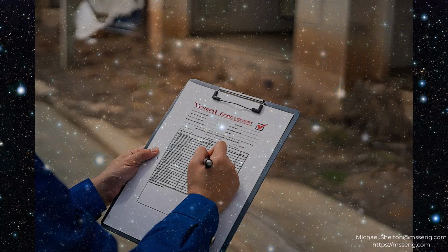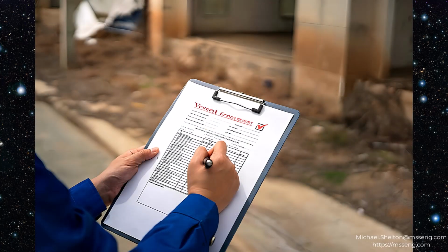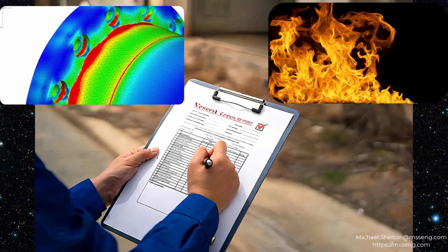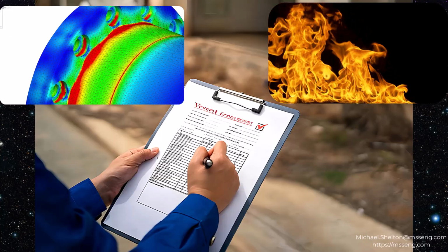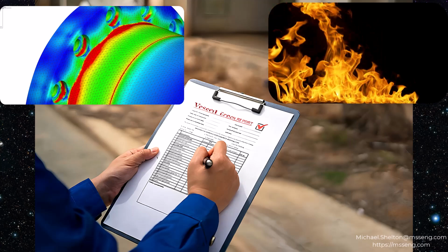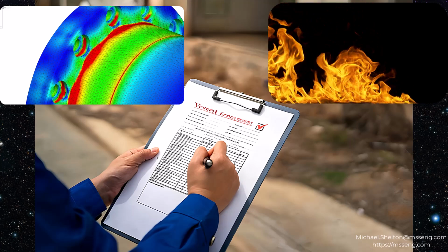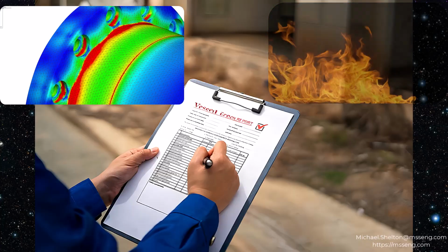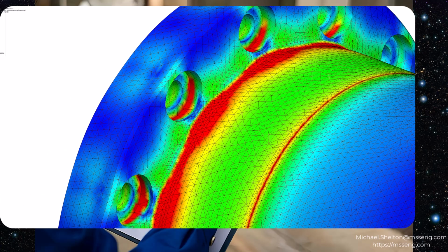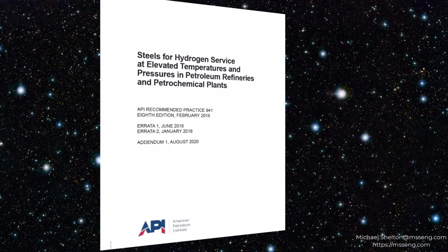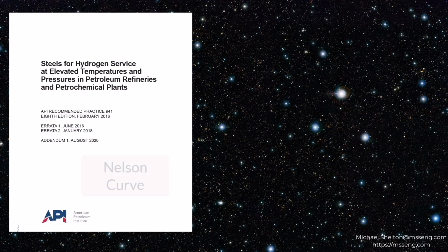An appropriately designed inspection plan for a vessel or piping undergoing HTHA will include high stress area identification as worst case. Since HTHA is both a stress and temperature phenomena, hot areas in addition to stress areas should be considered. In all, a carefully engineered inspection plan is required. Therefore, HTHA inspection requires sound engineering, usually finite element analysis assessment of the vessel, equipment to be inspected, and a comprehensive step-by-step plan. Normally, vessels which operate within 50 degrees of or above the metal's Nelson curve criteria, again API 941, will require a structured inspection plan.